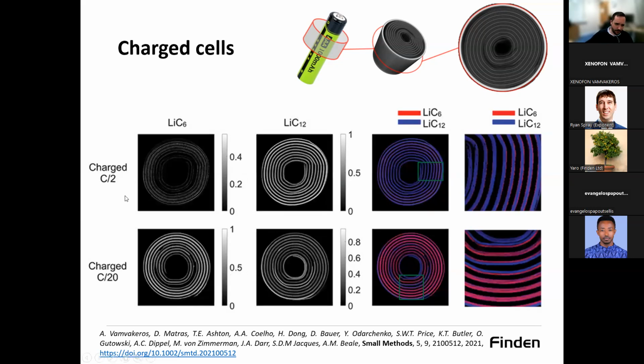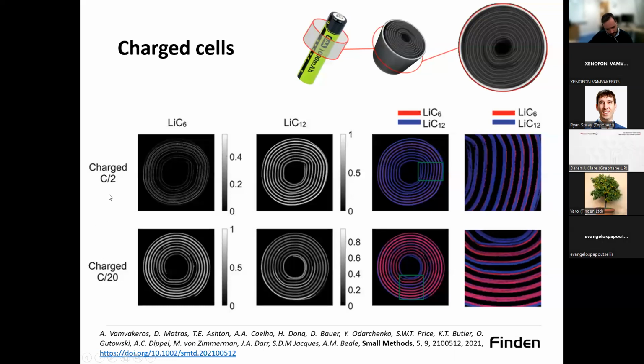Here we can see something about the charged cells. Again, it was fast and slow charged. We can see that the lithium carbon 6 forms, of course, first at the surface of the electrode. Again, I repeat, this is not a groundbreaking result, but you see the chemistry within a real device in real time.